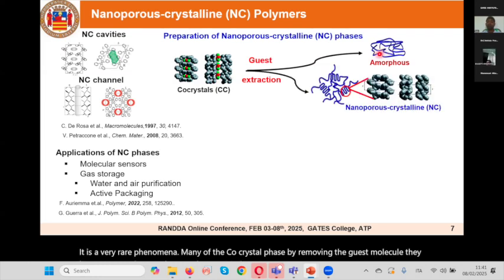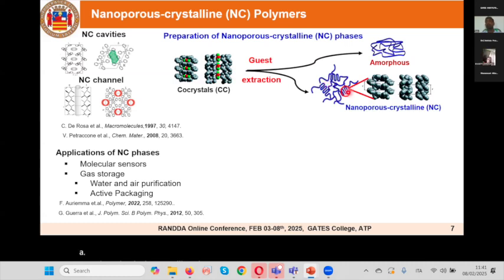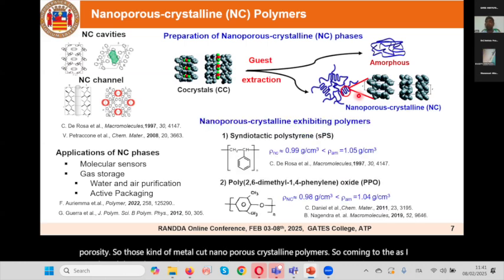But two specific polymers can form a nanoporous crystalline polymer. By extraction of the guest from this co-crystalline phase, they maintain the crystalline phase, and within this crystalline phase, they maintain the porosity. So those kinds of materials are called nanoporous crystalline polymers. As I mentioned, only two polymers exhibit the nanoporous crystalline phase. The first one is syndiotactic polystyrene. The second one is poly(2,6-dimethyl-1,4-phenylene oxide). Only these two polymers are known to exhibit nanoporous crystalline phases, and luckily both are commercially available.